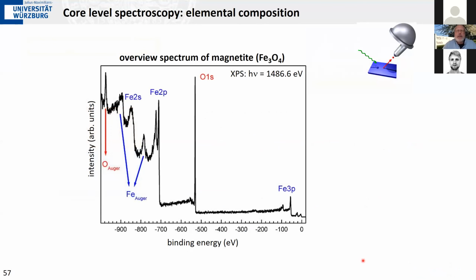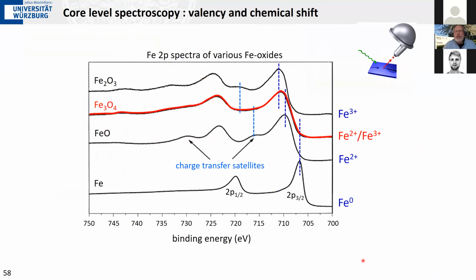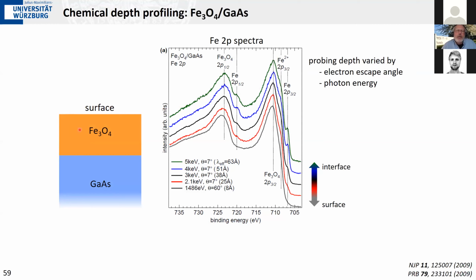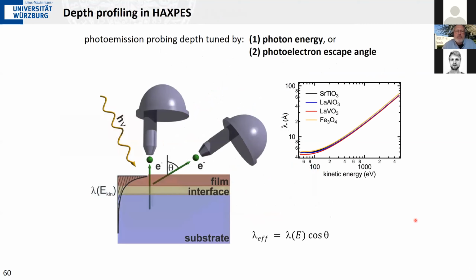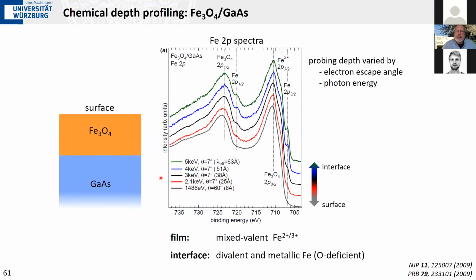And then you look again at the core levels of the iron in magnetite. We had studied this before, and you know now that we have certain fingerprints for the valency of the iron in there, and that we can then do by looking at such a film. And then what we change is the probing depth, and we do this by changing the escape angle of the photoelectrons. If we look in the vertical direction, we can exhaust the full probing depth. If we turn now the escape angle detection to a grazing situation, the electrons will come from a much thinner range, so we have decreased the probing depth, but we can also change the photon energy to increase or decrease the probing depth, and by that then do depth profiling.